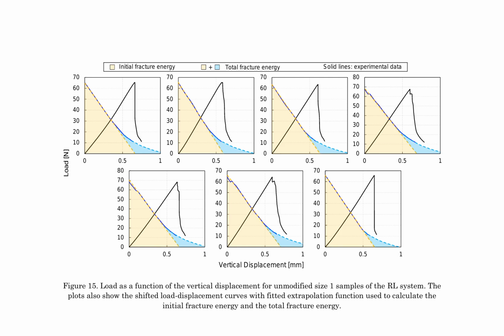The research paper presents an analysis of the fracture behavior in unmodified and thermally modified wood samples, focusing on the radial-longitudinal, RL, and tangential-longitudinal, TL, systems. Page 17 illustrates the load as a function of vertical displacement for unmodified size 1 and size 2 samples of the RL system, with Figure 15 and Figure 16 respectively.